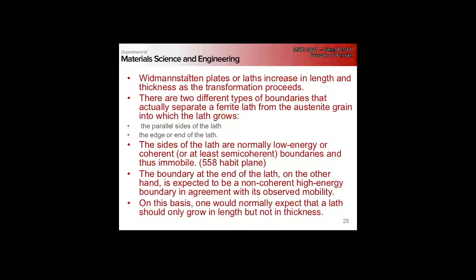Based on this simple analysis, we shouldn't expect to see much widening of the lath. We really should only see extension. But we do actually see the laths grow because eventually they come in contact with each other.